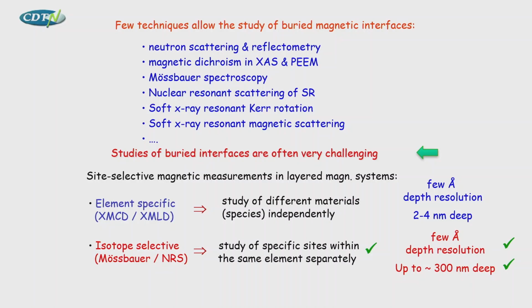That means you cannot go deeper than, let's say, 40 angstroms, something like that. That means the depth selectivity of X-ray absorption is really limited, okay? But if you play with isotopes, you can have a resolution in the monolayer regime, especially if you use synchrotron, and you can go really deep in the structures with that. This is a very interesting approach, okay?